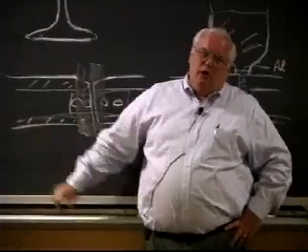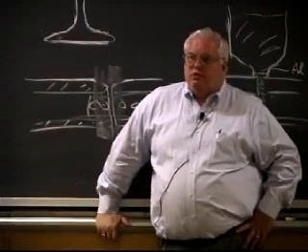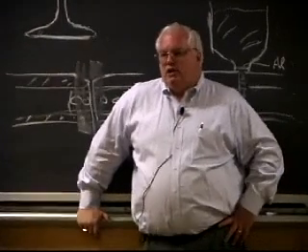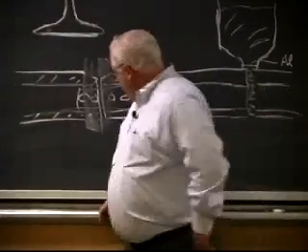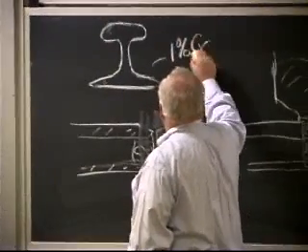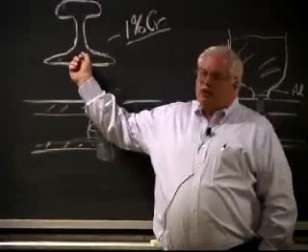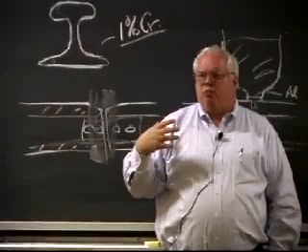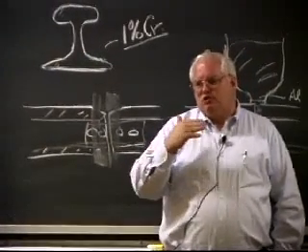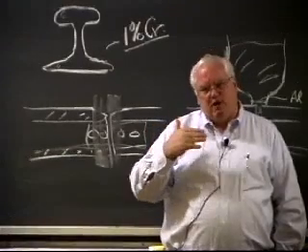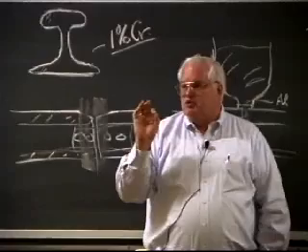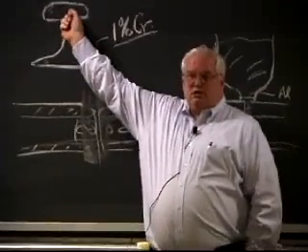Nowadays, more and more, and I don't know what the percentage is, it used to be like 10%, but it wouldn't surprise me if it's 20, 30, or even higher percent now, they use heat-treated rail. Now, one of the rails they used to use was a 1% chromium rail, which was not heat-treated, but at 1% carbon, the rail structure is basically what we call pearlite in steel, which is a mixture of iron and iron carbide. It's a very, very fine composite. And adding chromium to it gives you a much finer structure, and you get much higher hardness and much better wear resistance.